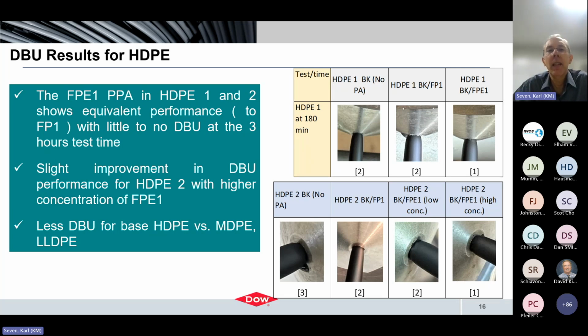Then we looked at the performance with the typical fluoropolymer processing aid. It's roughly the same. It may be slightly worse. And with the polar polymer additive, results look very good overall. With the high density HDPE2, which is a little bit higher density, we looked at two different concentrations, and comparing with no processing aid, you do see that improvement. We actually saw slightly better performance at the higher concentration of this polar polymer additive versus the lower concentration.